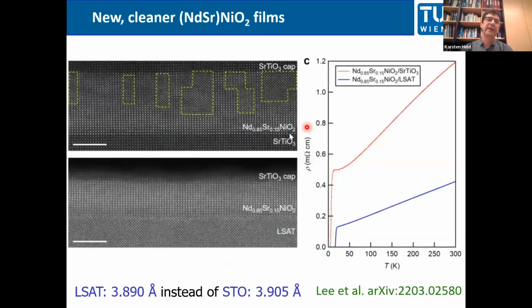Here, by the way, is the old experiments where you have a lot of stacking faults, and the new experiments don't have the stacking faults. It's a slightly different substrate, but that is less relevant here than getting rid of these stacking faults. You see that here the resistivity in experiment decreased by a factor of 3, and at the same time TC increased by a factor of 3 as well. The difference of the substrate could be maybe 3, 4, 5% in TC, but not such a big factor.